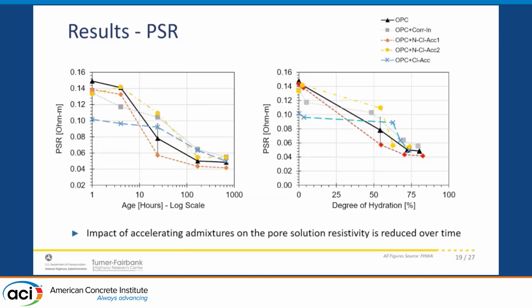So these are the pore solution results. One of the things mentioned in ASTM C1202, the RCPT ASTM, is that mixtures with corrosion inhibitors should not be tested because the results are not reliable. We show here that at very early age, the pore solution is highly affected by the presence of admixtures, but over time that effect reduces by a lot. Admixtures that initially increase the conductivity of your solution, reducing resistivity, ultimately don't necessarily have the same effect over the long-term tests.